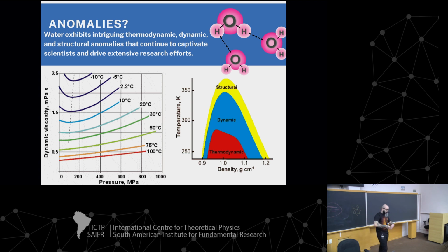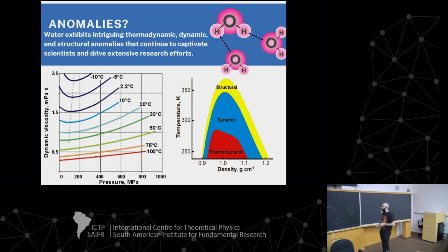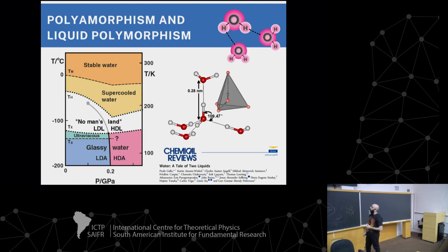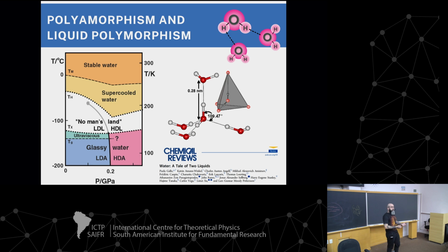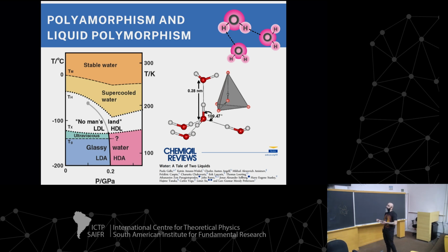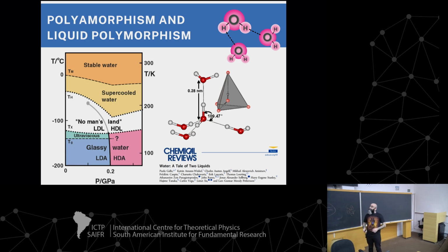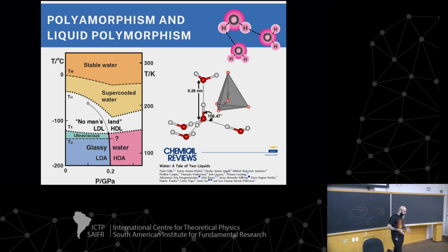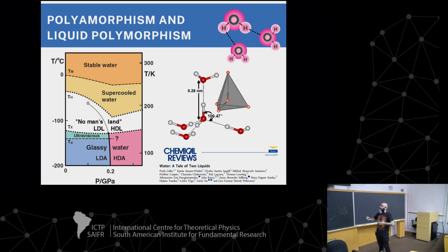So we can try to see the region in the whole T or PT phase diagram where water has these kinds of anomalies. And why water has these anomalies, you also heard a lot of people talking about. It's basically related to the fact that water is not only one liquid. It has two personalities, one with a low density, another with a higher density. And these personalities keep struggling. And so you have this phase transition that we believe is true, but we still don't have an experimental, how can I say, anyone who ever saw this in an experiment, but a lot of theoretical physicists and chemists already saw it in simulations. So we believe that simulations are working well and are correct.